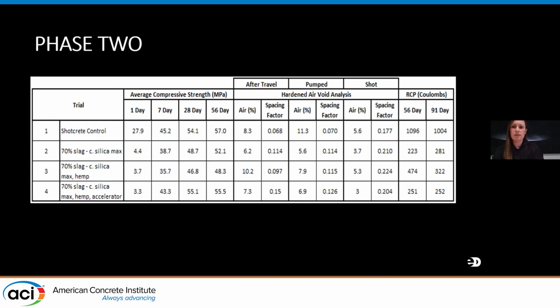Beyond the plastic properties of the mixtures and their suitability for use in these structural walls, the hardened shotcrete properties had to meet the requirements of CSA, the Canadian standard up here, class C1 and low shrink mix, and conform to the project specifications, which were even more stringent than the CSA. So the 28-day compressive strength results of each mixture were above 45 MPa, which exceeds the design strength of 35. The measured boiled water absorption values maxed out at 5.5% in 28 days for all of the mixtures, which is well below the maximum allowable of 8% based on CSA.